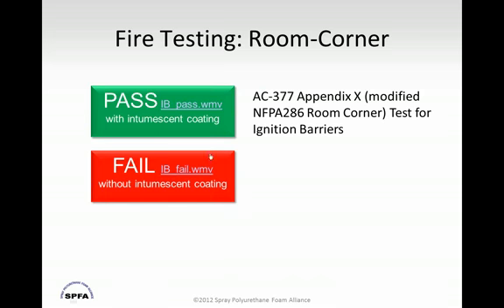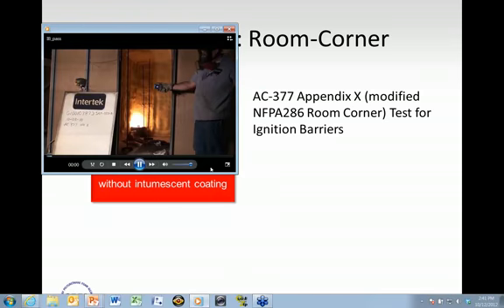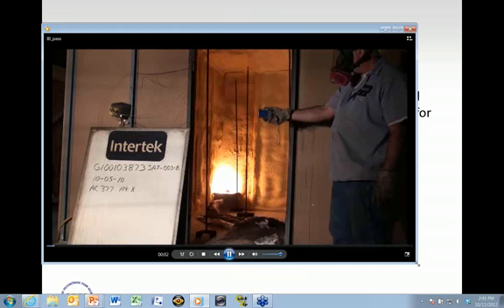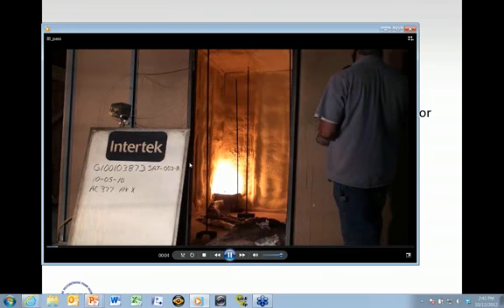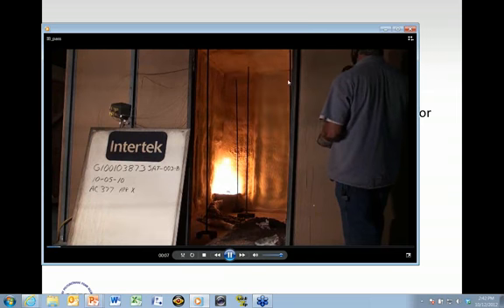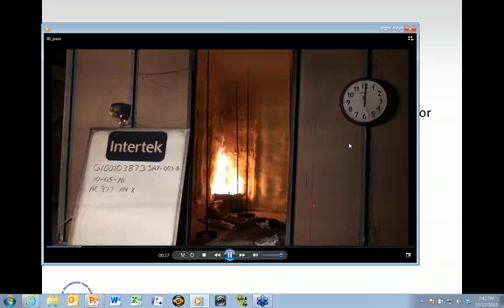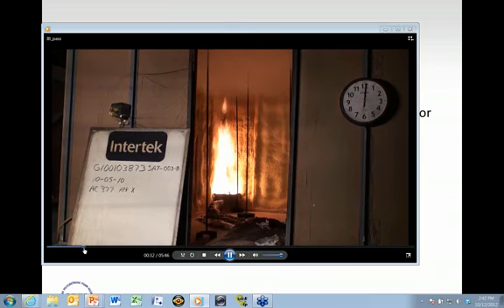So that was the baseline for which we did testing on what we call the ignition barrier coatings that are used over foam. So this is a test of a foam product with an actual ignition barrier coating. And you see here that there is a timer that this guy's standing in front of right now. He's going to move away from it in a minute, but it's an approximate timer. Now we're about 15 seconds into this test. And you can see that the foam, and here's our gas burner, and the foam is burning at a pretty stable rate. And this will occur actually with an intumescent coating. It's going to occur and last for a number of minutes. I'm not going to go through the whole 4 minutes and 18 seconds. I'll give you a quick snapshot here.